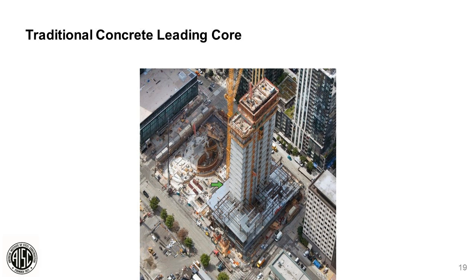And what you see is that the concrete core is let out well in advance of the trailing steel framing operation. The reason for that is that it takes nominally, very rough order of magnitude, about twice as long per floor to build that reinforced concrete core than it does to build that steel floor framing. And what we find is that the concrete core is the critical path of the project. All the elevatoring goes through that core. And so we started to scratch our head and say, how do we begin to improve the speed of construction of that core? How do we get it off the critical path? If you can get it off the critical path, every day saved is a day delivery of the project sooner to the client.